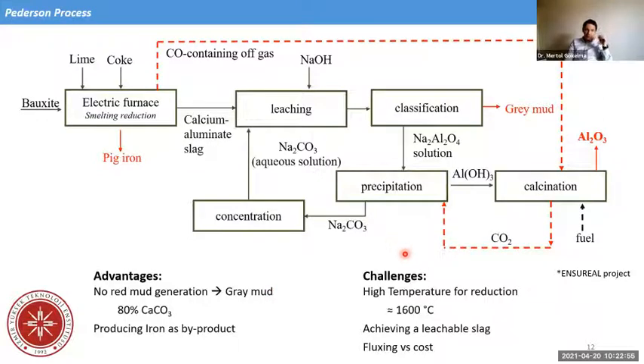The challenges of the Pederson process: we need high temperature for reduction. So we need an extra step, which is the pyrometallurgical step. It increases the cost, of course. And in my opinion, the biggest challenge in the Pederson process is achieving a leachable slag. Because when you produce iron and the slag here, this slag has to go for a hydrometallurgical process, because our target is alumina. This is our first target, not iron.